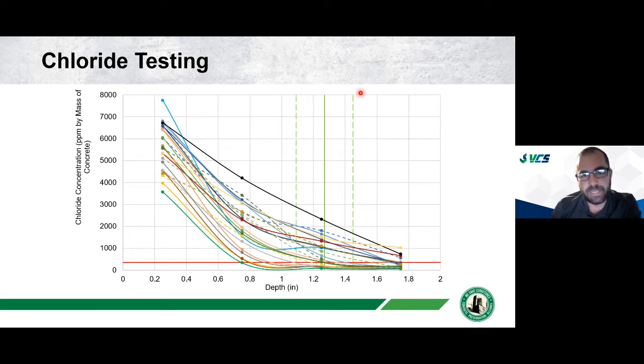And the green lines show the cover depth. The solid green lines are the average cover depth of the steel, and the dotted lines are plus or minus the standard variation. And you can see that almost all of the samples collected are well above the chloride threshold at the depth of steel. So if the chlorides are above the threshold at the depth of steel, the risk for corrosion is quite high. And not unsurprising on the structure. But obviously there are more concerns at these cracks.